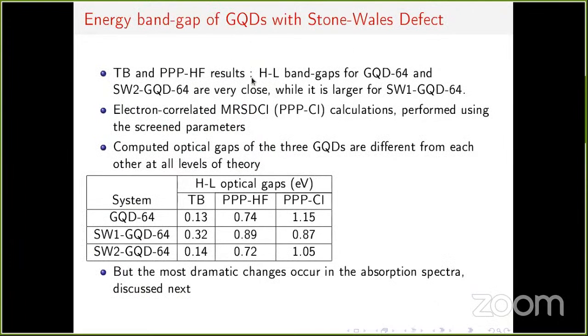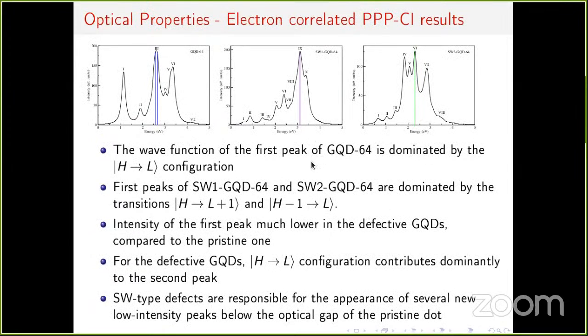Let us look at the optical gaps for the three structures. Again, we studied it at three levels of theory: tight binding, PPP model Hartree-Fock, and PPP model MRSDCI, which we call PPPCI in short. Here we used only the screened parameters, no standard parameters. For tight binding we get a very low gap, a somewhat higher gap with Hartree-Fock, and a much higher gap with the CI calculations. We note that the optical gaps of the three quantum dots are different from each other at all levels of theory. Although the difference at the tight binding level between the pristine and SW2 structure is not much, there are significant differences at other levels, at least 0.1 eV at the CI level.